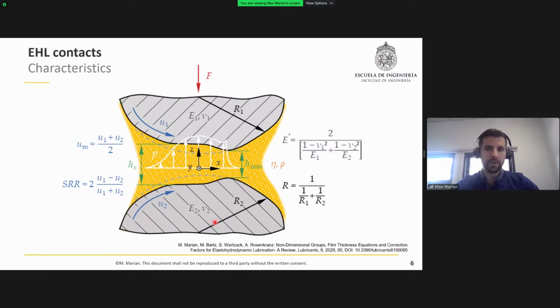Basically, the resulting pressure and fluid film distribution is determined by the geometries of the contacting bodies with radius r, for which we can calculate an equivalent radius, and the material behavior of the contacting bodies, namely the elastic modulus E and the Poisson's ratio nu, for which we can calculate an equivalent elastic modulus. Further, the kinematics influence the contact behavior, namely the velocities u of the contacting partners, for which we can calculate some characteristic properties like the hydrodynamically effective velocity um and the slide-to-roll ratio SRR. And finally, of course, as relevant lubricant properties, we have the density rho and the viscosity eta of the fluid that determine the contact behavior.